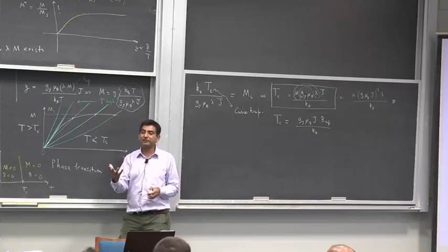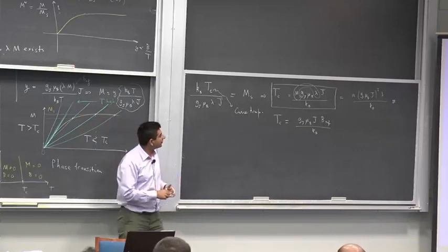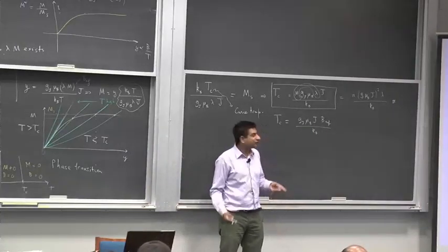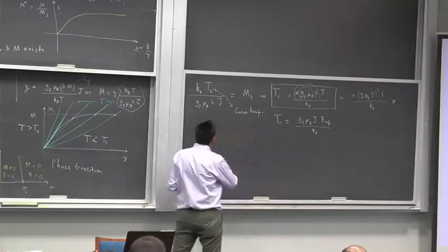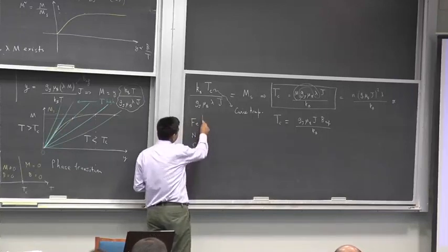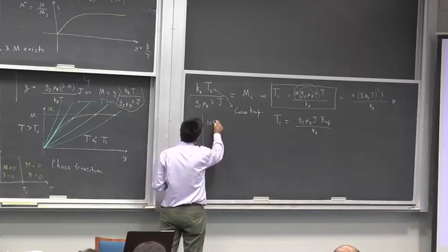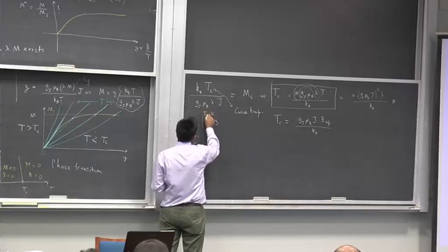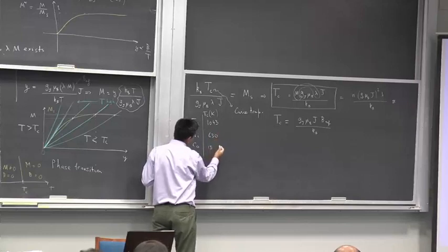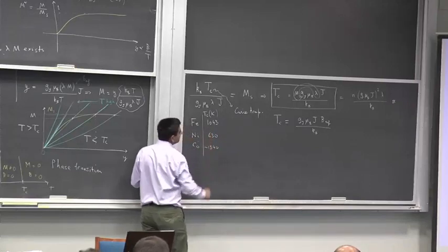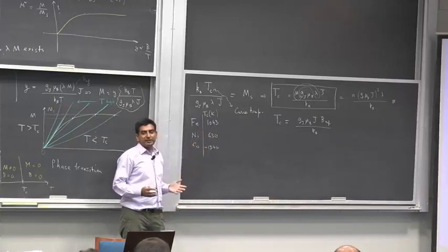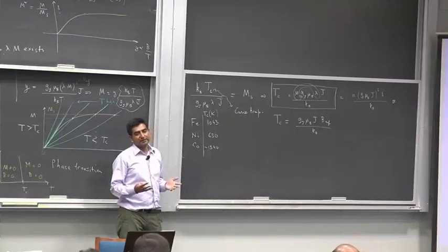Now we need to explore the origins of this internal field. But first of all, let's look at what should be the magnitude of this field. How large a field should exist? For that, we need to know the Curie points. Now, it's good to remember the Curie points of a few materials. For example, iron has a Curie point of 1043 Kelvin, Tc, right? Nickel has about 630 kelvins. Cobalt has about 1340 kelvins, about. Okay. So if iron is below 1043 Kelvin, it can sustain a spontaneous magnetization.